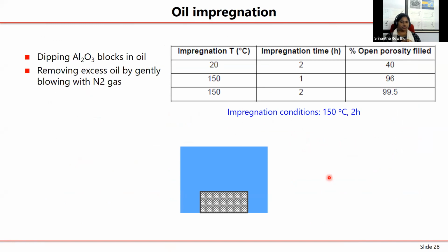Before we do tribological testing, we are not going to simply do a solid on solid, but rather we are going to impregnate the pores with a high viscosity liquid. If it is a high viscosity liquid, then typically impregnating at room temperature is going to be a problem. Whatever conditions you see in this slide are for the so-called Fomblin oil. Fomblin oil is a perfluoropolyether. Typically, people use it in vacuum pumps for very long periods of time. It can be used without significant evaporation.